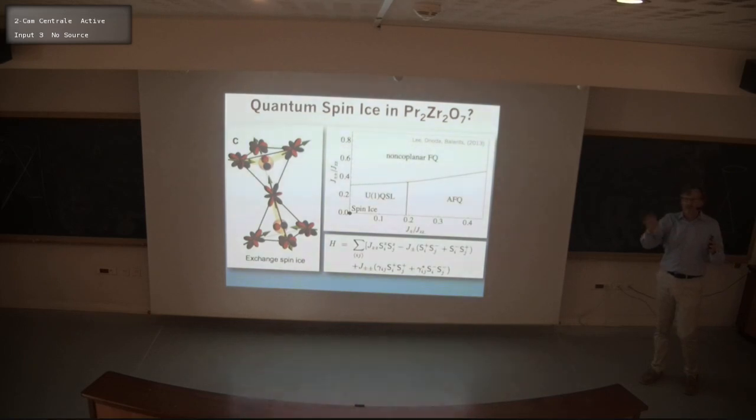And the Hamiltonian that we write down to think about the energetics of classical spin ice, maybe with dipole interactions and some exchange interaction, it actually will not be able to execute a spin flip. If you subject the spin ice manifold to that Hamiltonian and then project onto the ground state crystal field manifold again, then you'll just be back in the same state. So all of the dynamics is of a kind that we're not able to describe using our Hamiltonian at all. So it's a different kind of system.